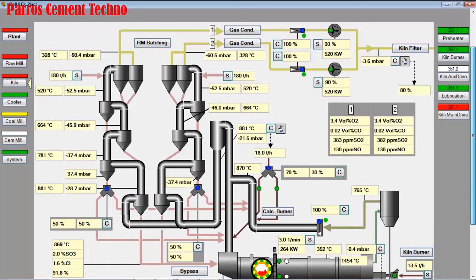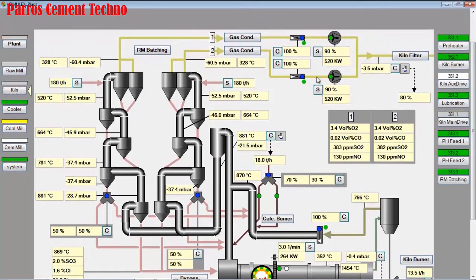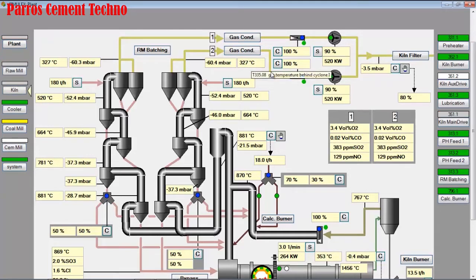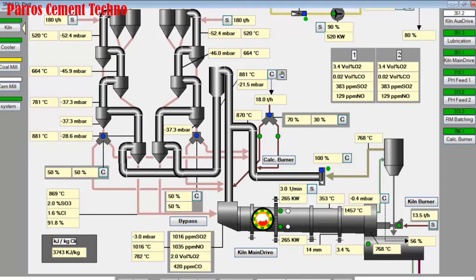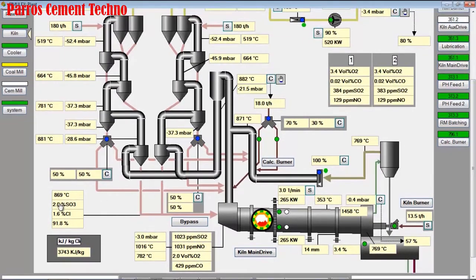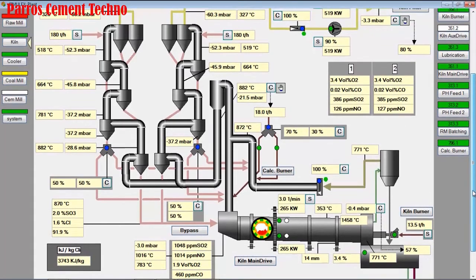The current kiln operating conditions: the temperature at the top of the preheater is 328 degrees Celsius, the kiln feed is 360 tons per hour. Free lime is still 3.4%, decarbonization is above 91%, and heat consumption is still 3,740 kJ per kilogram of clinker.